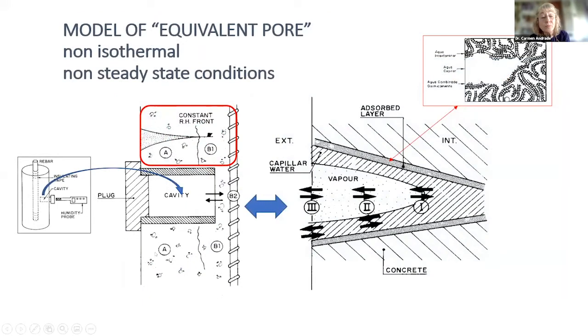And we had to produce this model, which we call the equivalent pore model, in order to interpret what is happening in the cavity and in the pores of the concrete. If we imagine the capillary pores, because the gel pores sometimes don't exchange water, you need liquid water in order to introduce water into the gel pores, but the capillary pores are those that exchange the water.